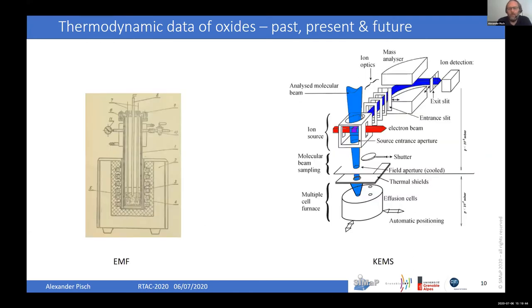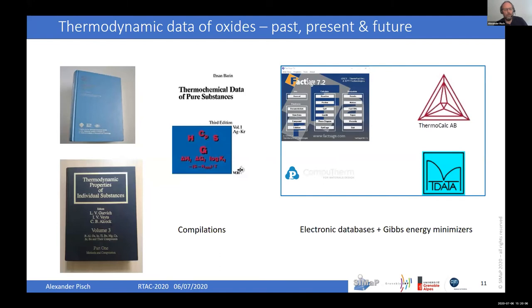Last but not least, you also have Gibbs energy-based measurements, so either electromotive force measurements here on the left side, or Knudsen effusion mass spectrometry. In both cases, you measure activities, and from these activities, you can derive Gibbs energies and get temperature data like this.